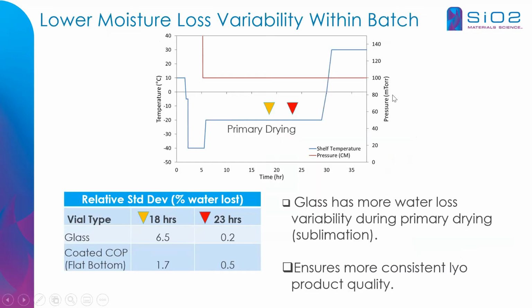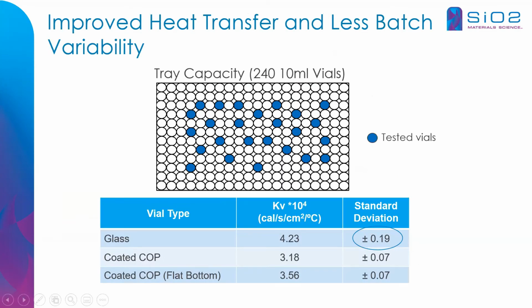And as you can see, let me just go back to this slide here. This is a study we did, a freeze-dry study of heat transfer, and the blue ones are the locations within the tray. Here you can see that the heat transfer rate is much closer to glass than the original heat transfer coefficient, and that's due to the dimensional consistency of our container. And then you can also see that by the standard deviation.